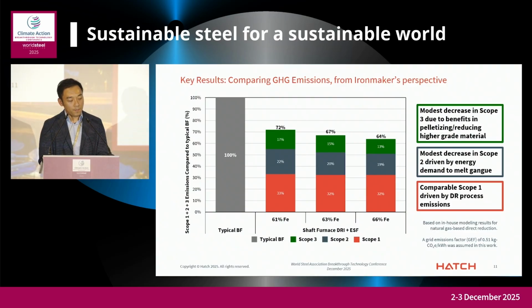But I think one of the things this doesn't account for is that mining operation has a relatively small emission footprint compared to iron making. So all the investment in OPEX and CAPEX in the mining and beneficiation operation doesn't get captured very well if you do a simple ton-for-ton emission calculation. And the second thing is, whereas you see the scope 2 emission drives a lot of it, we do see in the future, with the greening of the electrical grid, the gap in how much emission difference you can derive from beneficiating or not beneficiating closing even more. So I guess the general conclusion is beneficiating Pilbara iron ore does help reduce emission, but not by too much, and that gap is expected to shrink in the years to come.